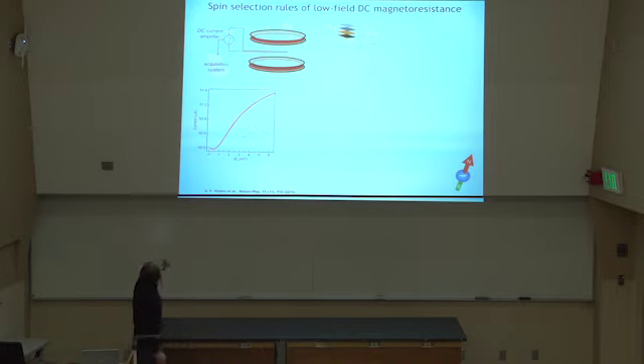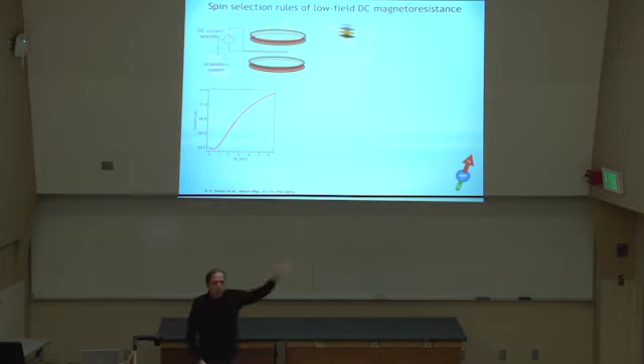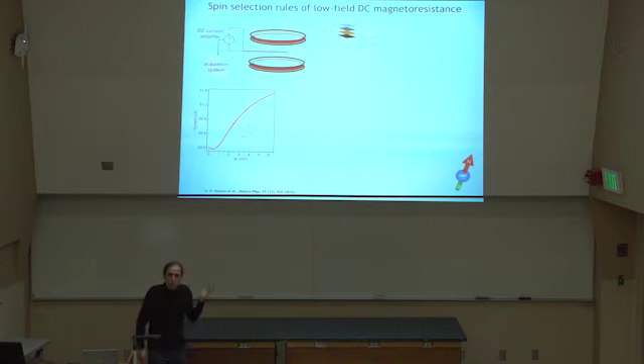The changes of your conductivity, the changes of your current on an incredibly small time scale is really huge. So this is not giant magnetoresistance where you have changes in the tens of percentages, because if you look at the fraction of change, well, it is large, but it's in the percent range, not in the tens of percent range. But the change per magnetic field is just outrageous. And how is this supposed to work? Why do these materials do that?